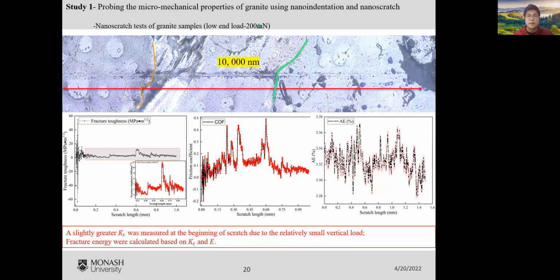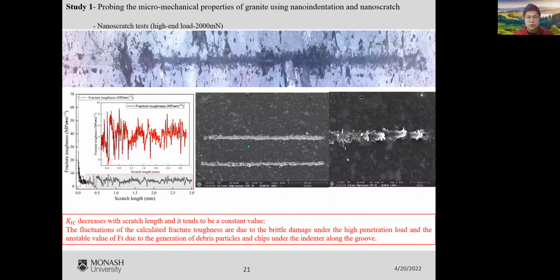We changed the end load, and we also used nano-scratch to obtain the fracture toughness, coefficient of friction, as well as the AE counts. Then we performed SEM to observe the scratch. It is found that the fluctuation of the calculated fracture toughness is due to the brittle damage under the high penetration load, and the unstable value of Ft is due to the generation of debris particles and chips on the indenter along the groove.